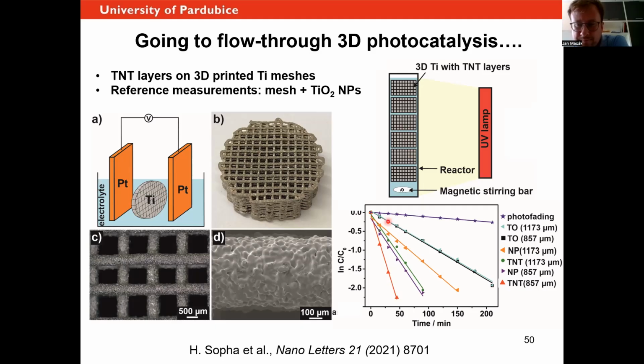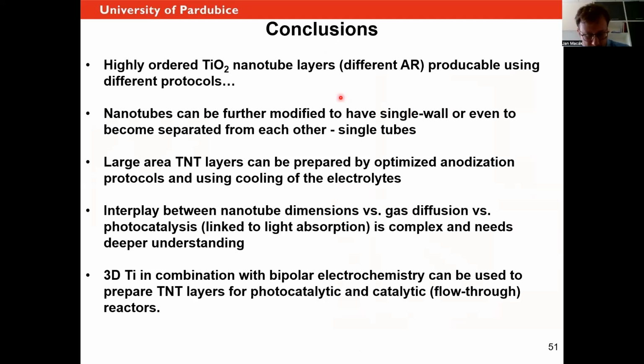And the catalytic rates actually that we got here are simply outstanding. These are probably the fastest photocatalytic rates we ever have seen, and that clearly shows that if you go from the 2D large area to the 3D area, so condensed area, the macroscopic volume, this is the way to go. So these are actually extremely efficient flow-through photocatalytic reactors that, in my view, are something like the first step of making really efficient cleaners that could be used commercially. With that, I'd like to conclude.